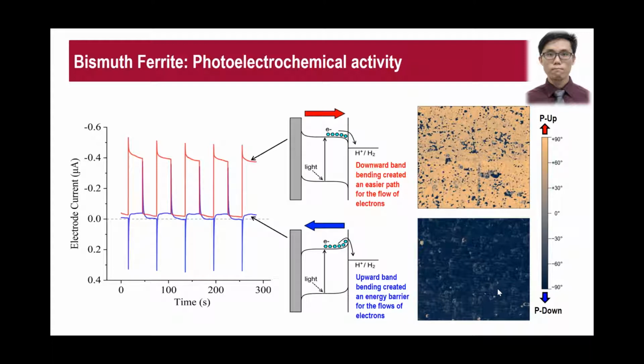And this depends on the objective of your measurement. For this case, we applied the electric field to the materials in order to purposely tune the polarization direction to P up and P down. And we want to see how the polarization can affect the flow of electrons due to the band bending between the BFO and the liquid interface.